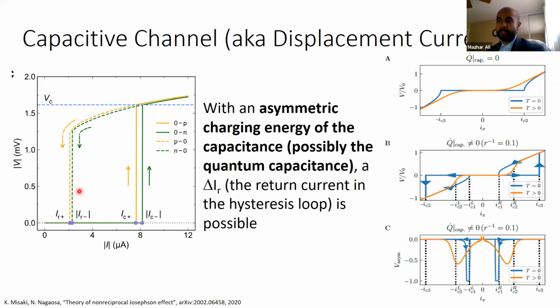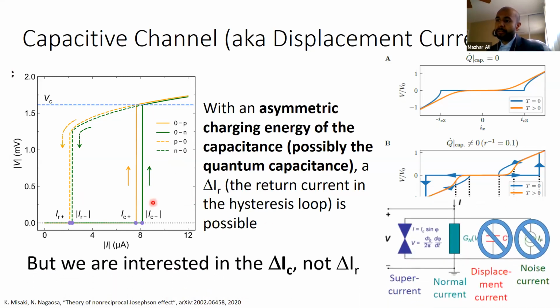This wasn't that large, and I don't want to stress on it today because that's not the point of what I'm talking about, but it might be exactly what we're seeing. But the bottom line is this work and this theory didn't go through the delta IC, the breaking and onset of the superconductivity, not the return of it. So the outsides of the loops. So this explanation, at least this current explanation, doesn't explain our results. So for the moment, we're gonna drop that as well.